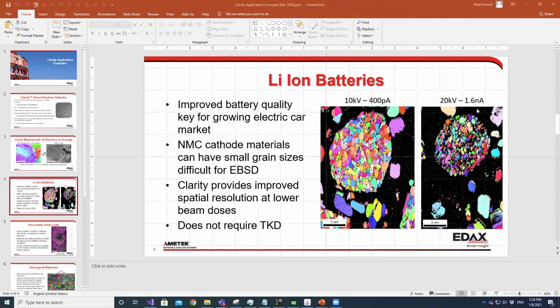This is at 20 kV, 1.5 nanoamps. We can resolve some orientations in that particle, but there's a lot of black areas where we're getting unresolved information near the grain boundaries, where patterns will start to overlap, just due to the fact that this is a lithium-based compound. There's a larger interaction volume. The band detection struggles a little bit. But if we drop this down to say something like 10 kV, 400 picoamps, you can see we get much improved spatial resolution on these type of materials.